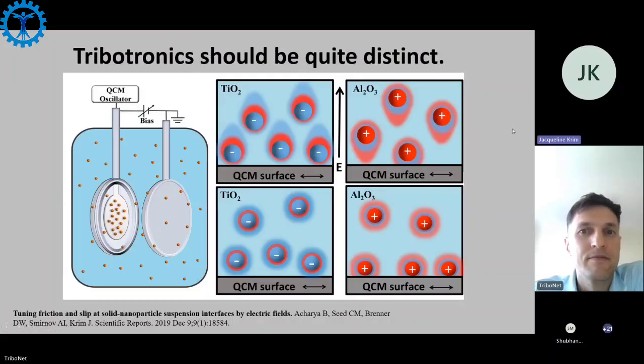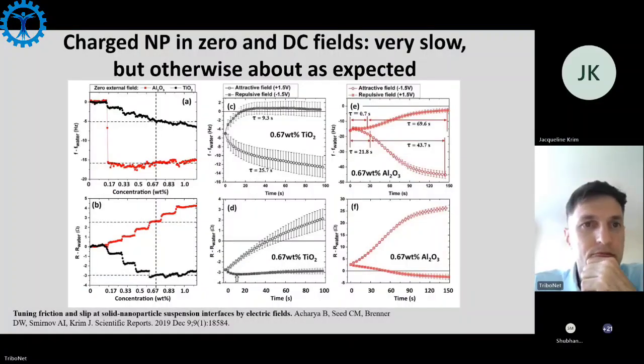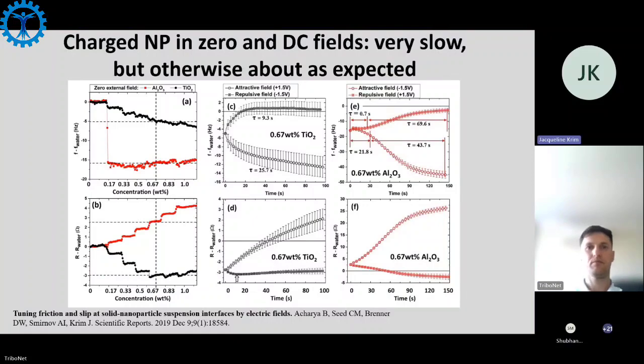Okay, so we took these different wetting and different charged particles, aluminum oxide and titanium oxide, and measured them on a quartz crystal surface with different bias levels, and we should see very different properties. So let's go to the next slide. And we did. I'm not sure that's a surprise, but it's interesting to look at it.